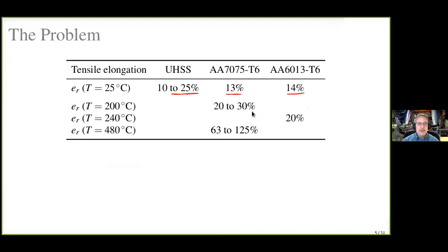But if we go to elevated temperatures, say 200 degrees Celsius for 7075, we are now suddenly getting formabilities, or at least tensile ductilities, which is one aspect of formability, that are very competitive with the steels. So this is a potential solution to making the components in this material. Some caveats I'll talk about in a moment. 6013, another alternative. Again, you go to a higher temperature. If you go to hot temperatures, I consider these temperatures here to be warm temperatures as far as aluminum forming goes, whereas this is going to be a hot temperature. We can get really great ductilities here. So these warm to hot forming temperatures offer some potential for making parts like the B pillar.